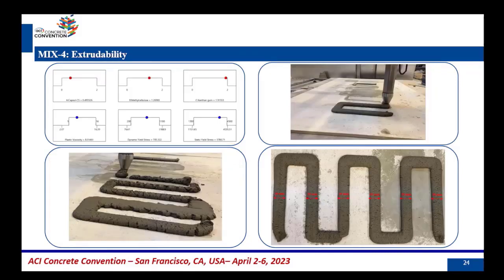Finally, for mix 4, we tried a different xanthan gum type in this case, but that led to a rise in the water requirement, and you can see surface cracks in this case because of the high water demand of the mix. But the mix has good extrudability in terms of dimension consistency and conformity. The only defect in terms of extrudability was the surface quality. That was not good. You can see a lot of surface cracks in this case.